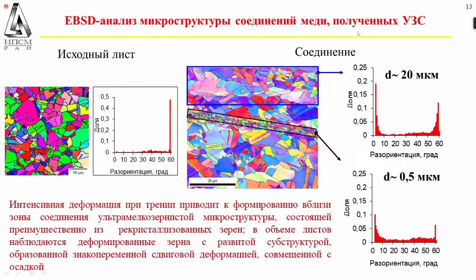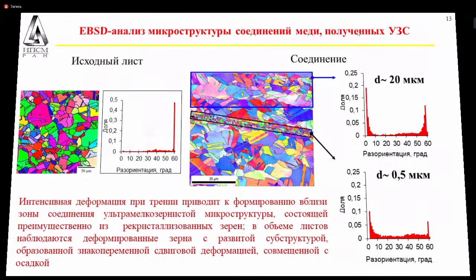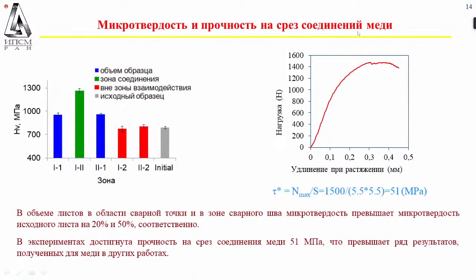You can also see the EBSD method, which shows that at the area of the welding seam, there happens recrystallization, which causes the ultra fine grain structure. And because of the oscillating and high-speed deformation, there appears a formation of a developed structure. And in comparison with the original leaf, the texture is changed.